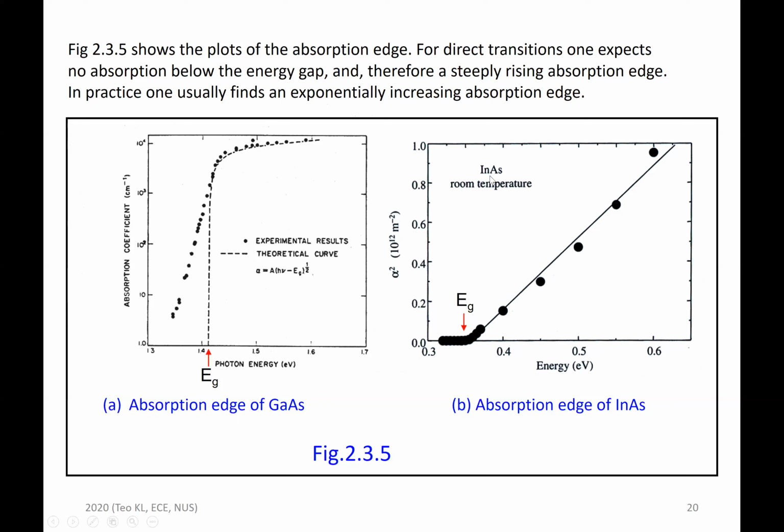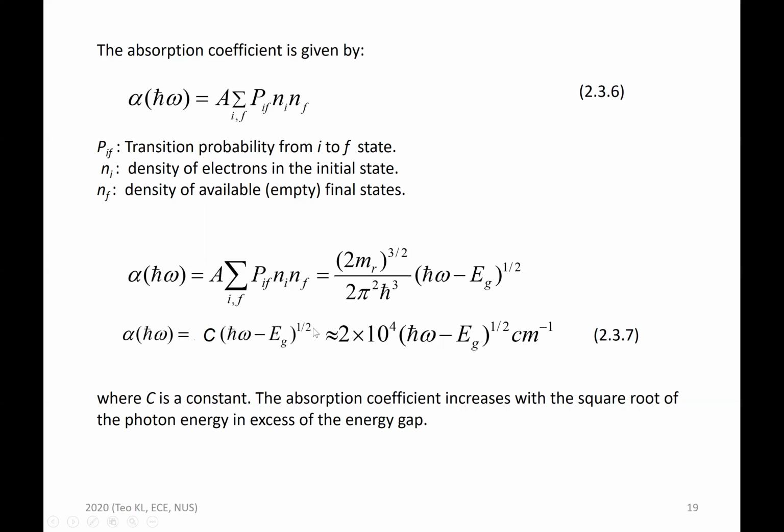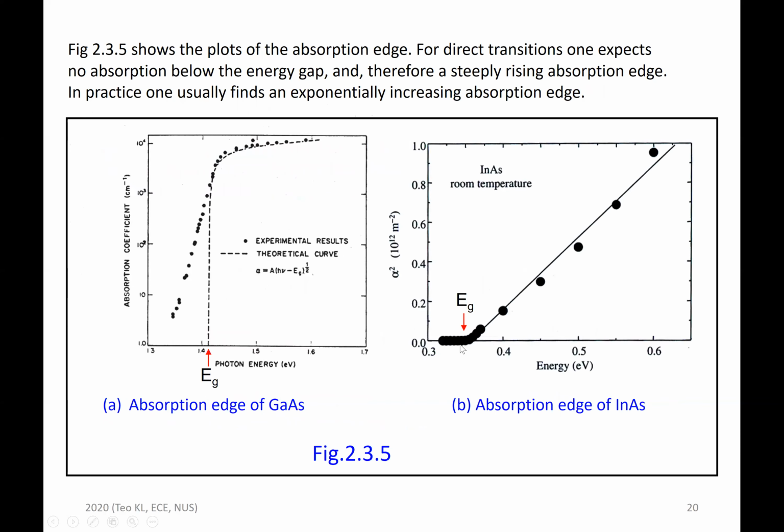Now, another experiment: indium arsenide, where you measure the absorption coefficient as a function of photon energy. If you take the square on both sides, then you can plot alpha squared as h bar omega minus Eg, multiplied by a constant. So you should get a straight line of alpha squared as a function of h bar omega. Again, the point where alpha squared equals 0 defines the band gap. So for indium arsenide, the band gap down here will be 0.34 eV. This part is straight, and this part has no signal.